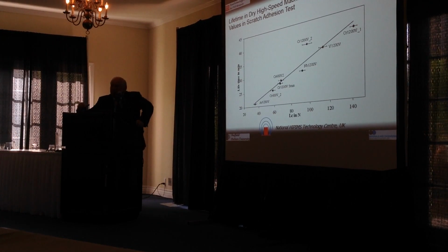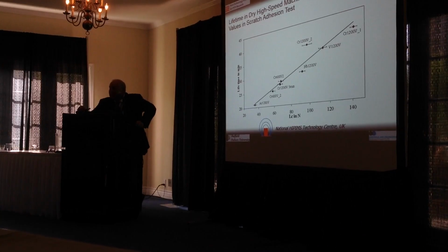What is very important to be understood for this type of materials is that because of their very high hardness, they're also highly stressed. So therefore, a good nanoscale multilayer coating or superlattice coating is a coating which is very strongly bonded to the substrate. This is a published work which we did in our lab in 1998, I believe, where we showed that the lifetime of an end mill is proportional to the adhesion of the coating deposited on this end mill.